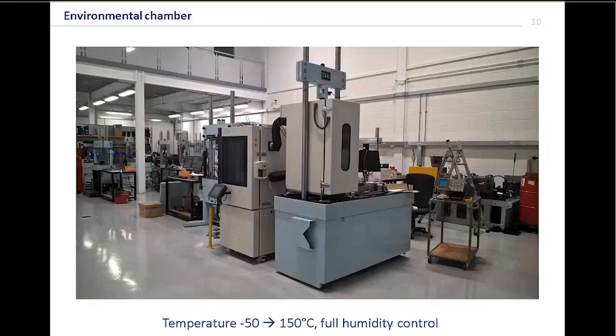As well as going hot, then we can go cold and humid too. So this is a picture again of an environmental chamber. This we can control the temperatures between -50 and +150, and it's also got full humidity control. And if you were to open the door to this today, you'll see that there are engineering polymers and things like that that we can test in that, which are particularly sensitive to humidity.